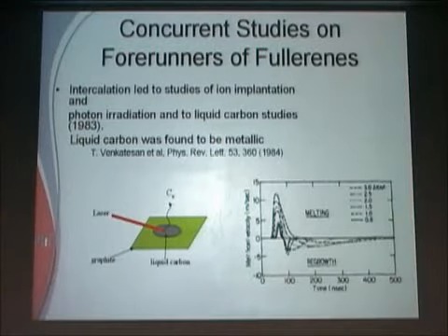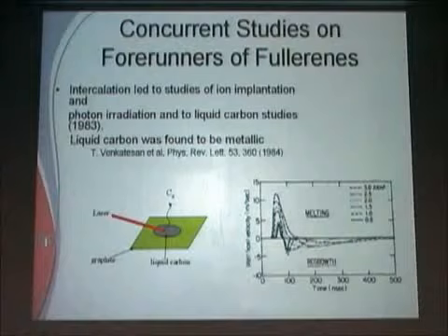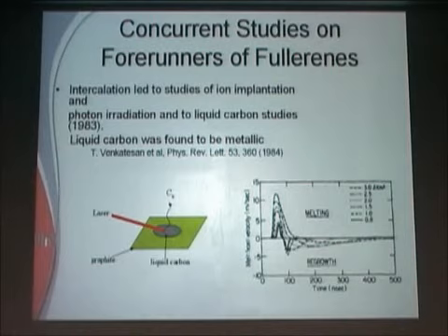While we were doing intercalation, we expanded our repertoire. We started intercalation in 1973, and about one decade later we started other things. The part important for carbon science was an experiment done to study liquid carbon — we wanted to find out whether the liquid form of carbon was conducting or was a semiconductor. That was not known at that time and was a rather fundamental issue. The result was that liquid carbon is metallic.